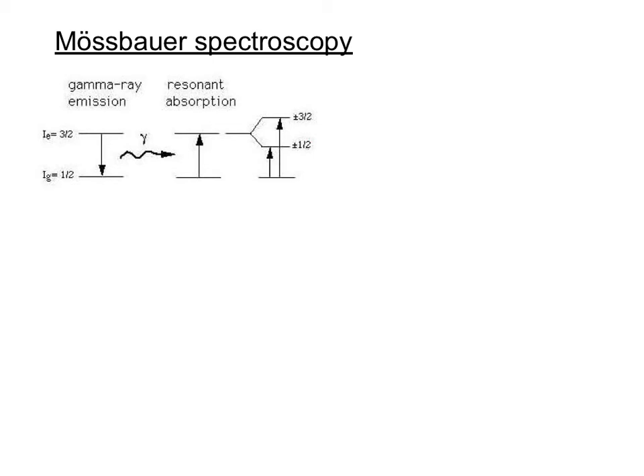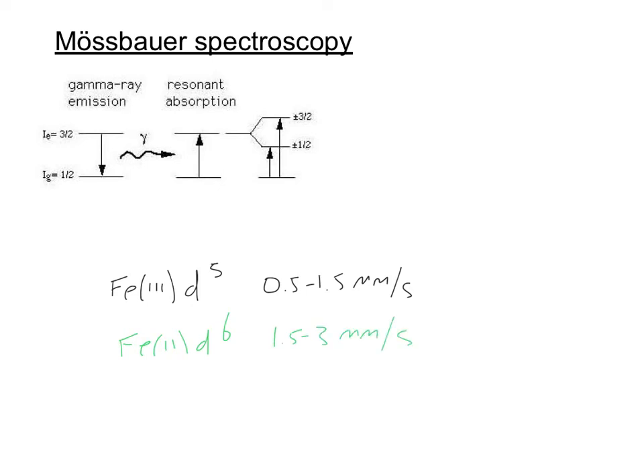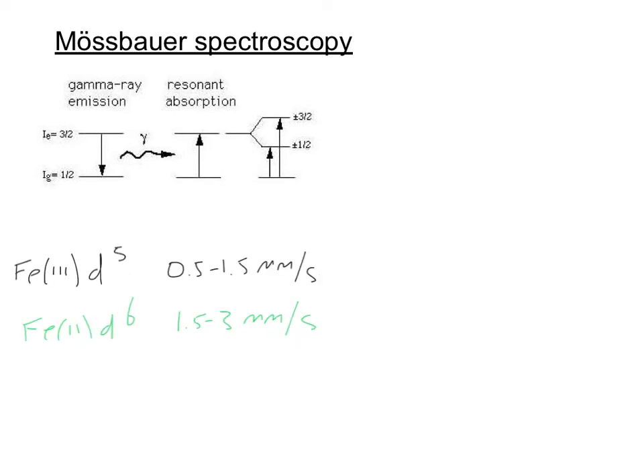So for a high-spin iron 3 with 5d electrons, that gives a spherically symmetric electronic configuration, so this delta E is low, on the order of 0.5 to 1.5 millimeters per second. On the other hand, iron 2 with similar ligands has a non-spherically symmetric electron configuration, and the delta E is on the order of 1.5 to 3 millimeters per second.